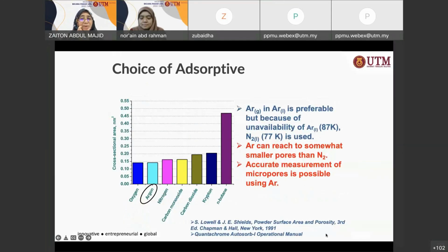So this is on the choice of adsorbate here. For surface area analysis, we use inert adsorbate gas: nitrogen, argon, krypton, some inert gas. But sometimes, if you want a reactive adsorbate, these are more for chemical reaction. I've used hydrogen when I was looking at hydrogen adsorption on carbon nanotubes. That was a very long time ago. But other than that, I've not used other adsorbates. Some people use carbon monoxide, carbon dioxide. Even carbon dioxide can also be used for surface area measurement.